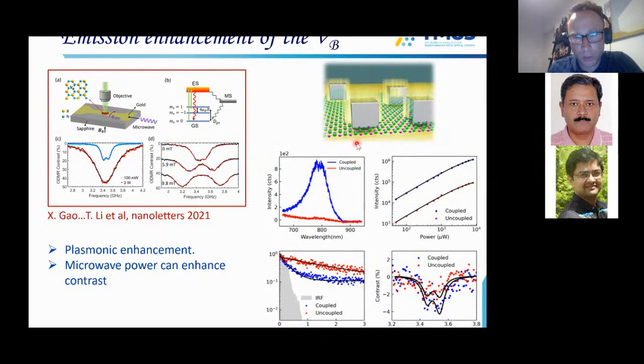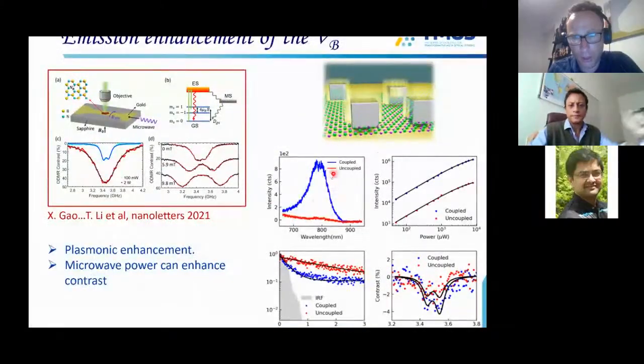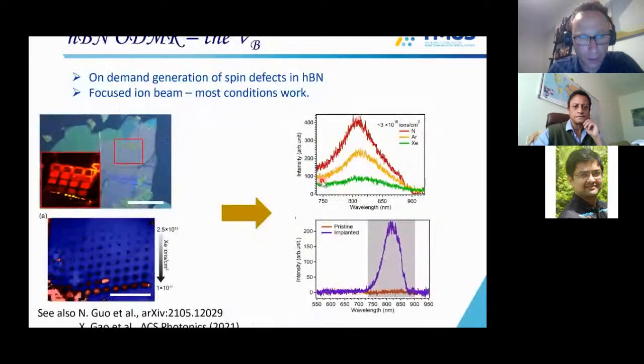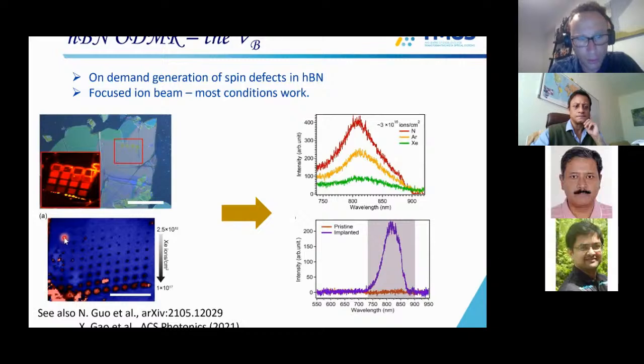So let me just tell you a little bit about the limitations of the system. So maybe I'll stay on this slide. As I mentioned, we don't know the zero phonon line, and we also cannot make them singles. So all these measurements are done on ensembles, and here you see that as we reduce the radiation dose, we really cannot get any single emitters. The emission simply disappears at some point. So the non-radiative transition rates are very, very high.